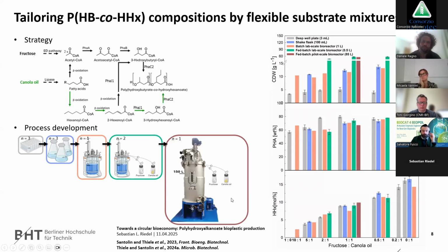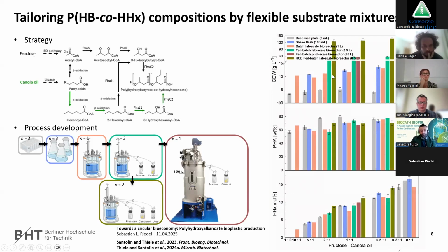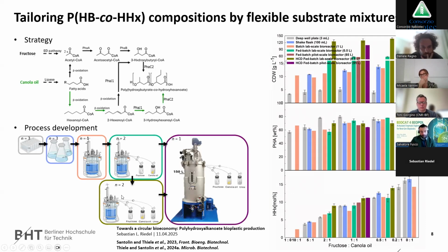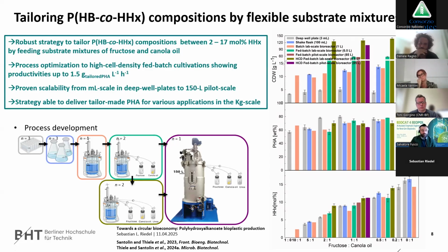And this was scaled up to the pilot plant again, which was successful. But then we increased it in the lab scale to 150 gram per liter, and then went back to the reactor where it also fits in. So there we can, as I said, produce different materials in kilogram scale for partners for different applications. So sometimes you need more HHX, sometimes you need less. So it depends also on the application. And this is here the productivity, for example.